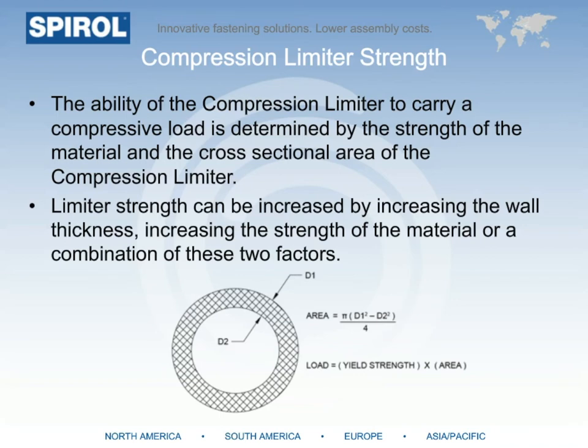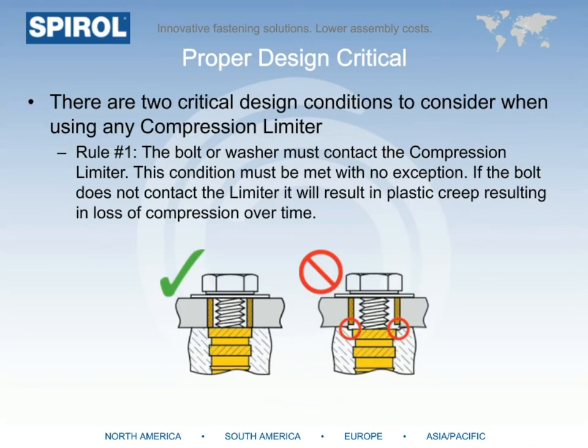There are two critical design conditions to consider when using any compression limiter. Rule number one is that the bolt or washer must contact the compression limiter. This condition must be met without exception. If the bolt does not contact the limiter, it will result in plastic creep and ultimately loss of compression over time. Now, the image on the right would not be acceptable if the bolt was fully torqued down. In this case, the compression limiter isn't doing anything at all. It's just adding cost to the assembly with no value. The image on the left shows a proper bolted joint.